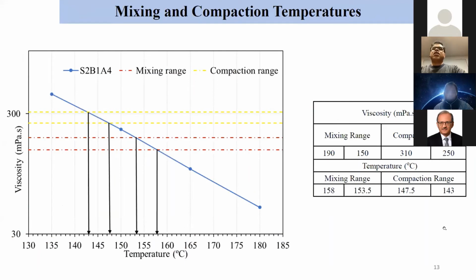Then the next slide is showing a typical curve of how we found the mixing and compaction temperature. For mixing, we know the viscosity is 170 millipascal second plus or minus 20. That's why the upper bound is 190 and the lower bound is 150. That is my mixing viscosity.